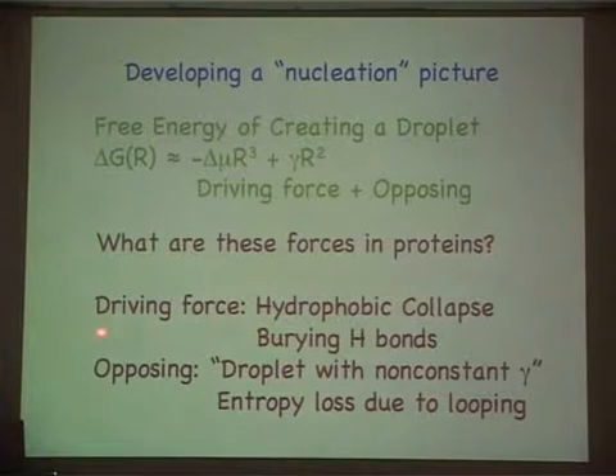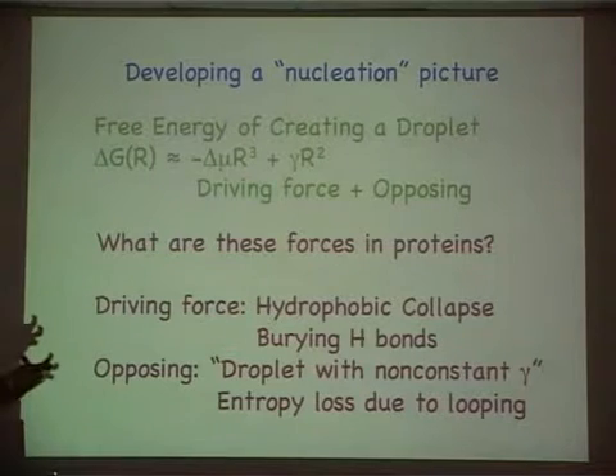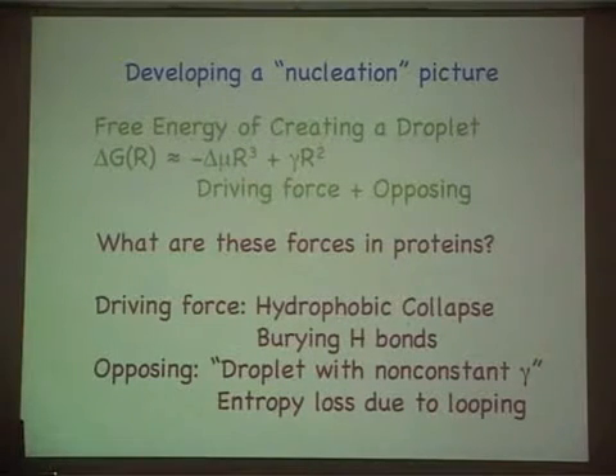Here, the driving force is, nominally speaking, a hydrophobic collapse. The hydrophobic residues want to be clustered in the interior of the protein, exposing the hydrophilics, which are on the outside. So that's one driving force. But we also learned a little bit, and this is increasingly becoming important, that there are many cases in which the burial of hydrogen bonds is a driving force, and there are no easy ways to write down energies in terms of this droplet-like picture in the nucleation picture for folding, although I'll show you some tentative attempts to try and do that.